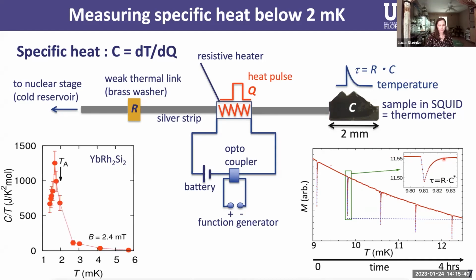And this is the specific heat that we measured using this technique. So this is now plotted versus temperature. And you see we can have a very pronounced peak at around 2 millikelvin, which is where the transition occurred. Now I've plotted this as specific heat divided by temperature. That's convenient because now I can calculate what entropy is involved, how many states are involved in this phase transition, by calculating the area under the curve.